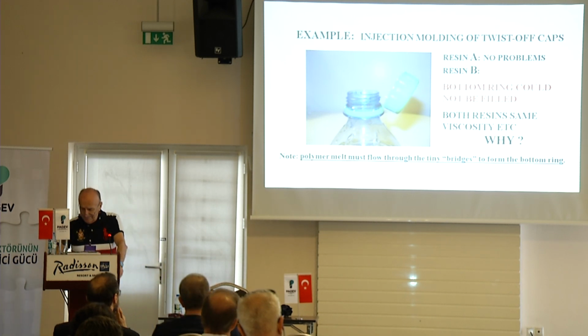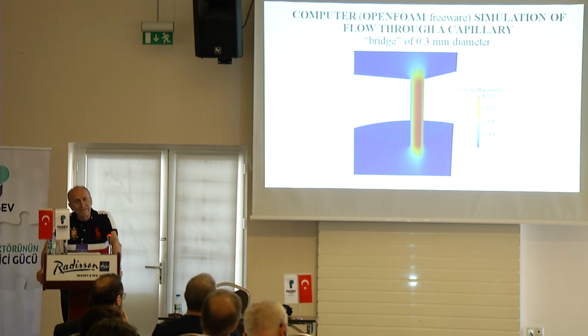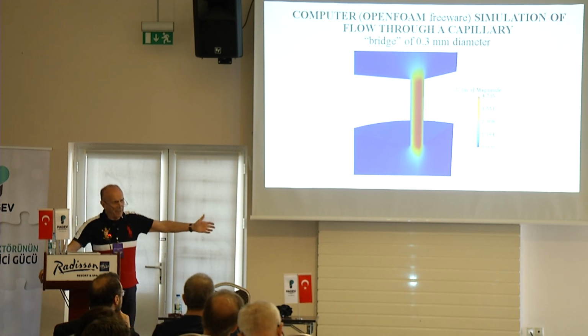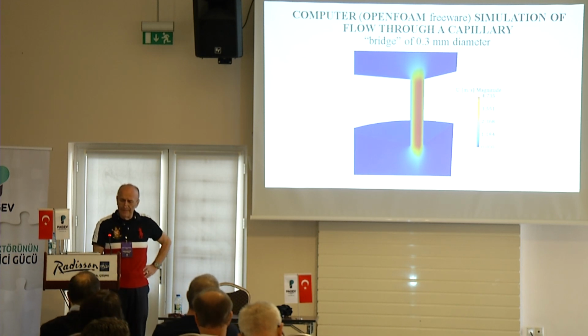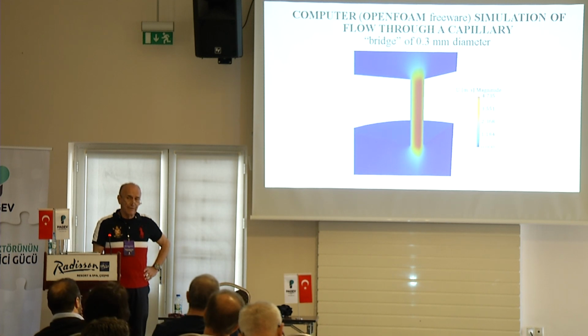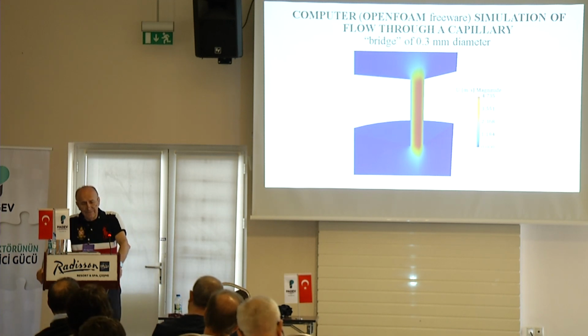So what happened? We did some calculations of the shear rate. We actually did some very simple calculations, and then we followed it with a computer simulation of the flow through this tiny capillary of 0.3 millimeters, all right?